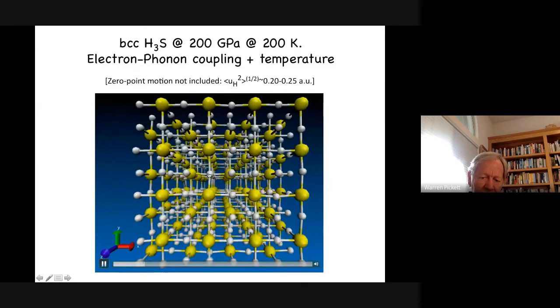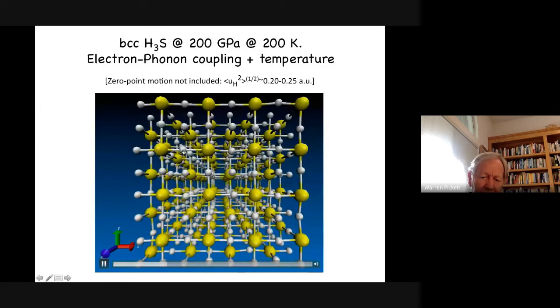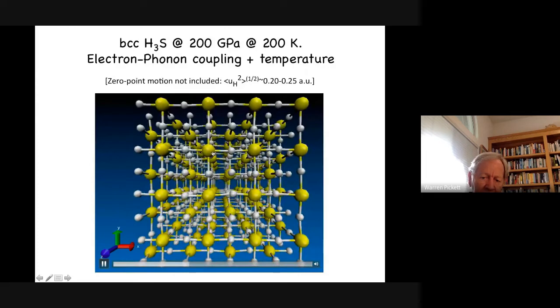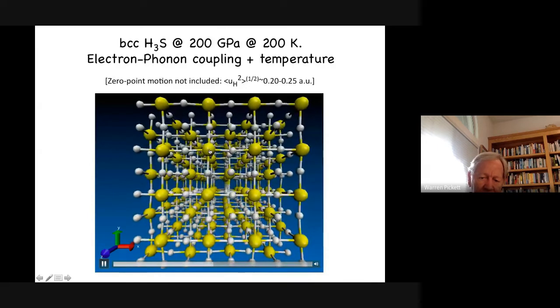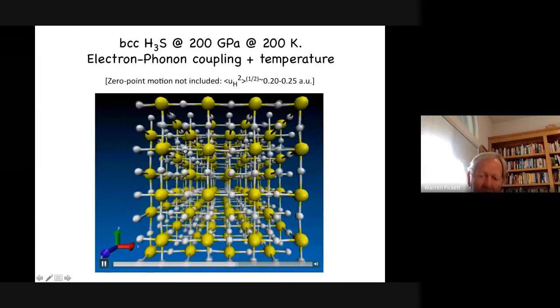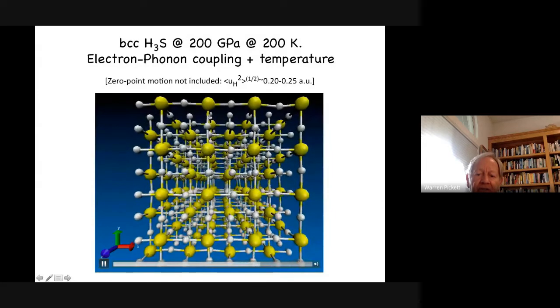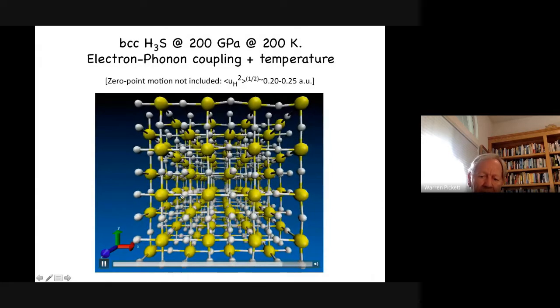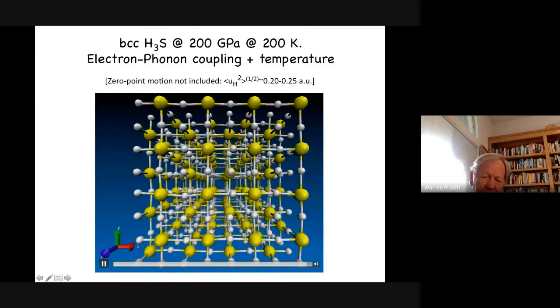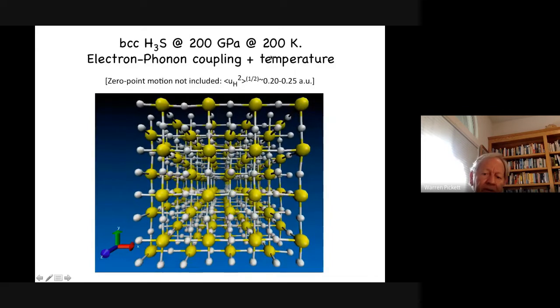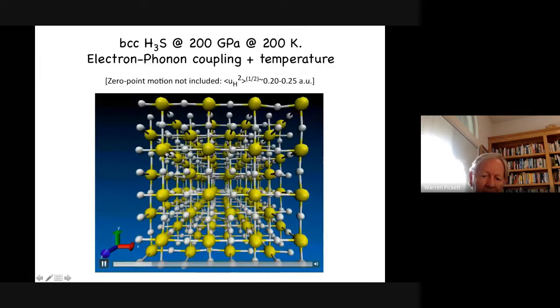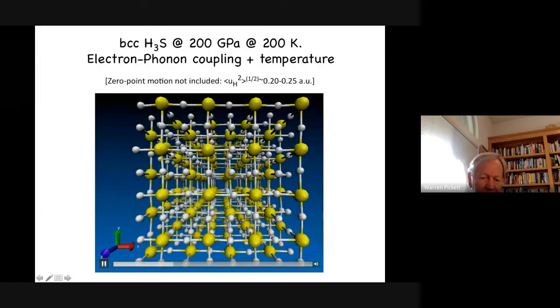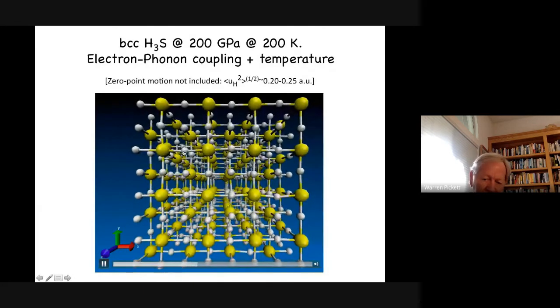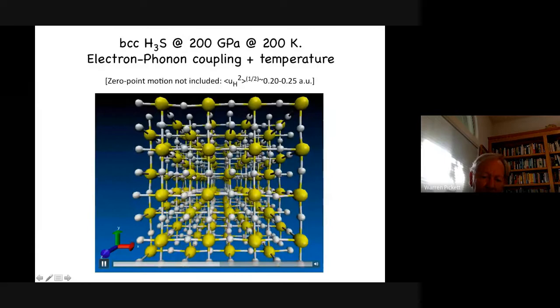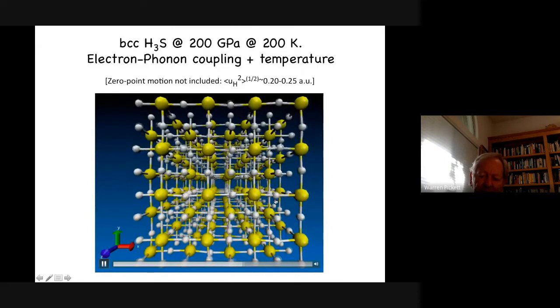The main thing you see here is how much the hydrogens move. Sulfur is much heavier. It has a weight of 32 or 34. Hydrogen is 1. So you can hardly see the sulfur move. And in a normal material without hydrogen, you would hardly see anything move at 200 Kelvin. But here the hydrogen displacement is very, very large, very interesting. And there's been quite a bit of theoretical study of that.